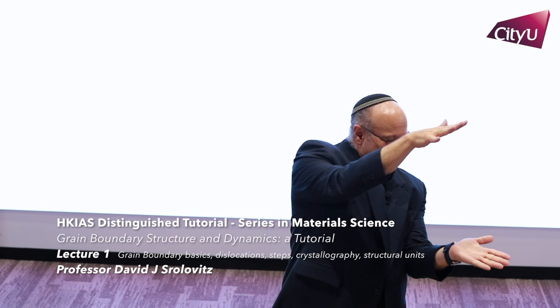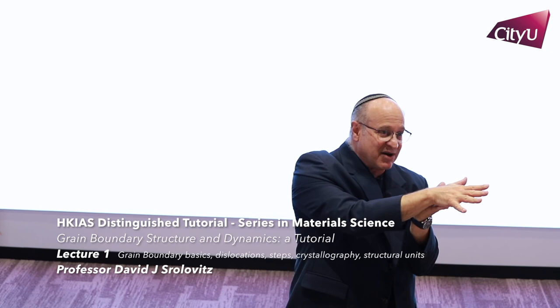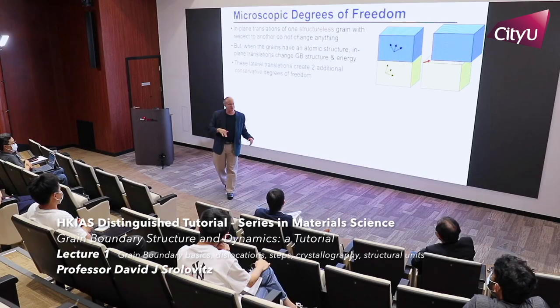And why does that matter? Well, it matters because there are actually atoms there. If I take a grain boundary where I put it together like this, and I slide it some arbitrary amount, the structure of those two boundaries will be different. So that's a microscopic degree of freedom. If I tell you the crystallography, I've told you nothing about the microscopic degrees of freedom.